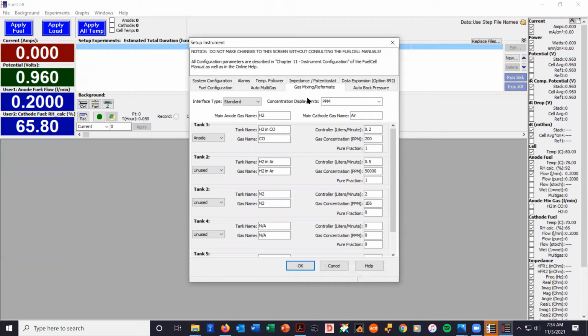We can start with 21, we can start with pure oxygen, but we can also take air, which is mostly nitrogen, dilute air with additional nitrogen, and end up getting lower and lower concentrations of oxygen. They call these mass transport limiting experiments, and you end up getting something called the oxygen transport resistance. So it's the resistance to oxygen diffusion through the gas diffusion media, as well as the catalyst layer pores, basically.